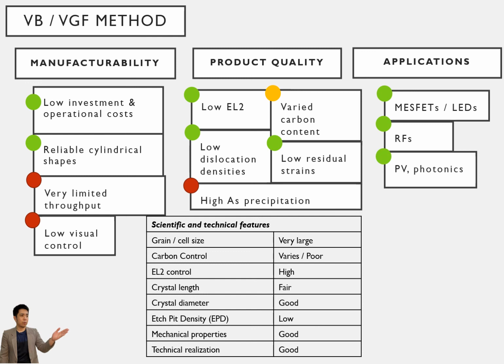We do have to keep in mind to control the impurities such as carbon and arsenic precipitates by annealing the grown crystal, which adds to lower productivity for these methods. But considering that the future will start to shift towards gallium arsenide devices, both VB and VGF methods seem good techniques to cater to the increasing demand.